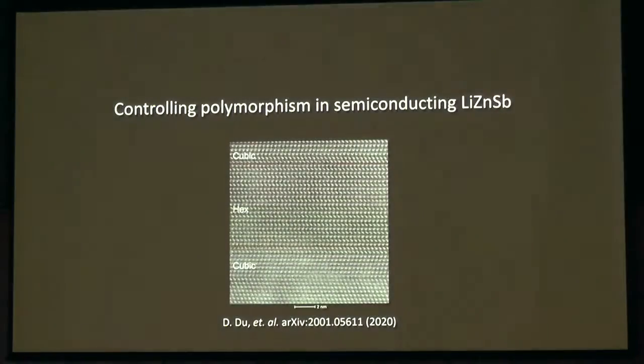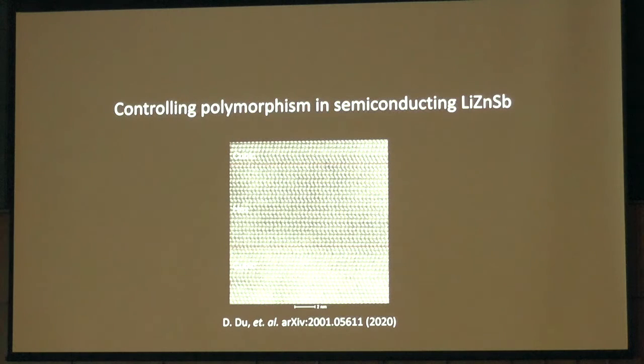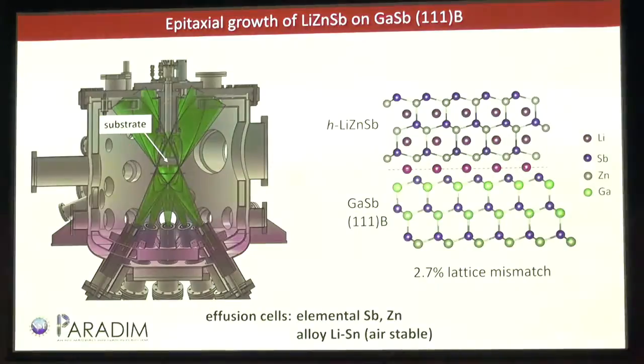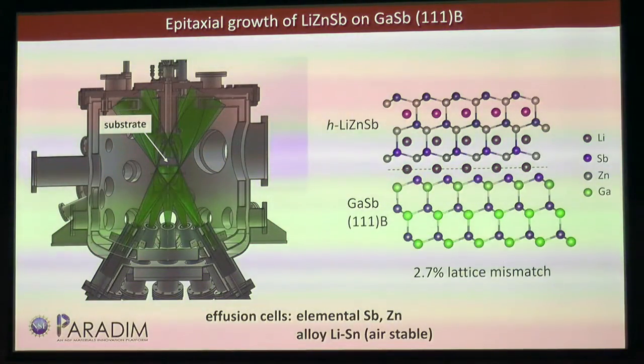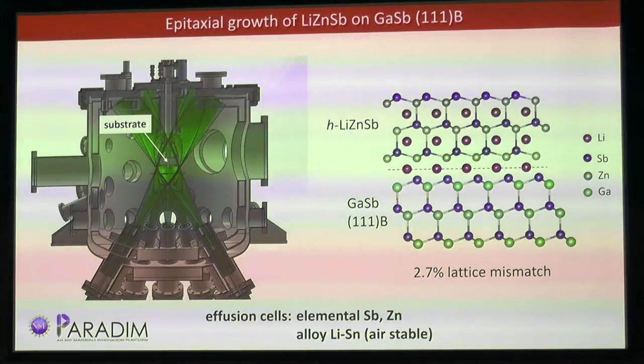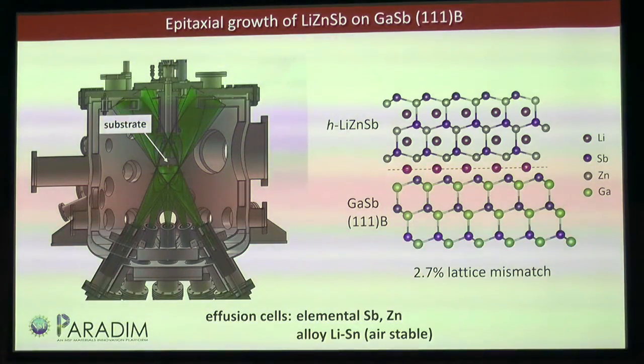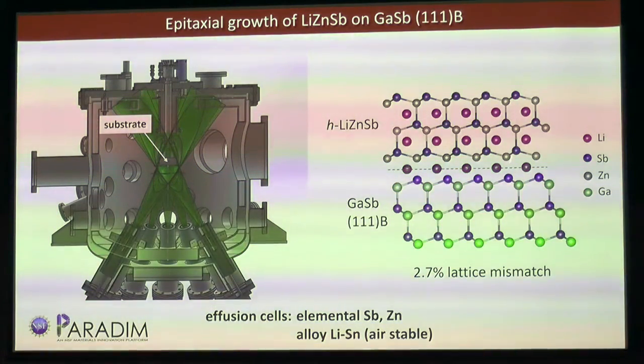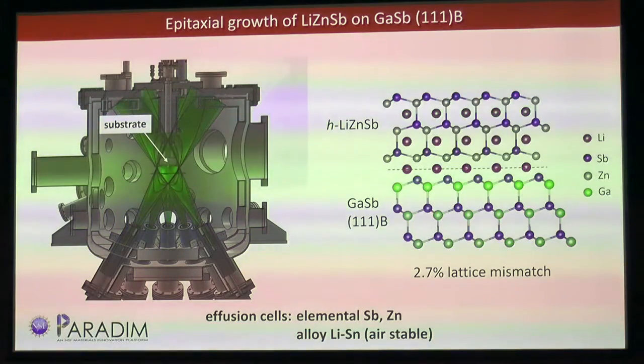Okay, so I'll start out by talking about these hyperferroelectric candidates, the ones that are natively semiconducting. And here the story really is, even before we demonstrate switching, we have to just control the right phase, okay? Here's a cross-sectional TEM image of one of our samples. One of the compounds we started looking at was lithium zinc antimony. Again, it's this compound right here. It's a stuffed wurtzite structure.